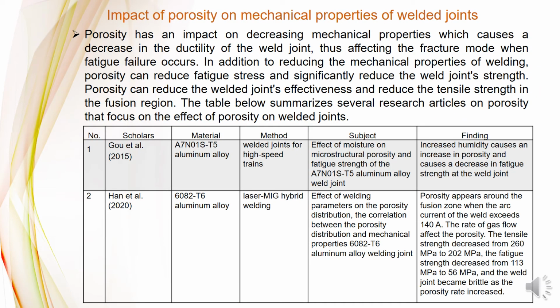Impact of porosity on mechanical properties of weld joint. Porosity has an impact on decreasing mechanical properties, which causes a decrease in the ductility of the weld joint, thus affecting the fracture mode when fatigue failure occurs, in addition to reducing the mechanical properties of the weld joint. Porosity can reduce fatigue strength and significantly reduce the weld joint strength. Porosity can reduce the weld joint effectiveness and reduce the tensile strength in the fusion region.